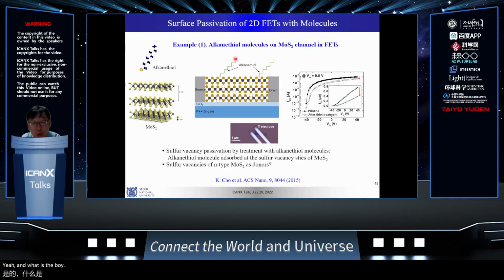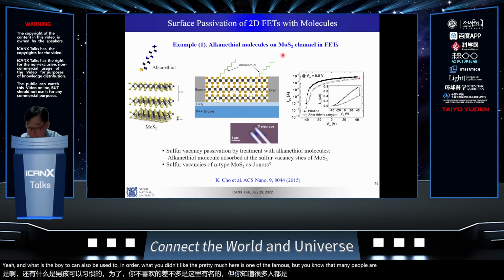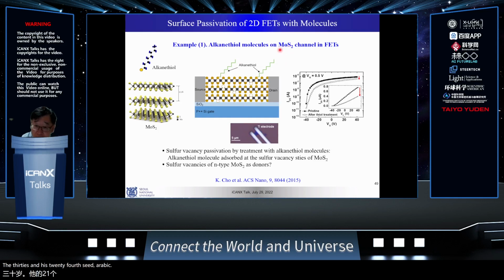And what else? The molecule can also be used with other materials, like 2D materials, one of the famous materials that many physicists and engineers study. This 2D material, particularly MoS2, is known to have a lot of sulfur vacancies. Schematically here is a sulfur vacancy, and this is a kind of mechanism for why MoS2 is n-type. If you use a alkanethiol molecule treatment, the thiol sulfur end group will likely bind to the sulfur vacancy. The sulfur vacancy is an n-type donor, but if you passivate it, you reduce the donor concentration. By applying this, the conductivity decreases and the dopant charge density decreases, so we observe a current decrease.